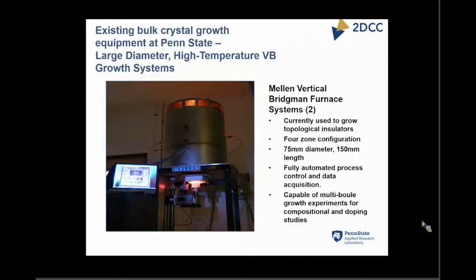And these are the systems that were currently used to start the growth of the topological insulator materials. These are 4-zone configurations. They've got 75 millimeter diameter capability, again, fully automated. And one of the things we've done in these furnaces over the years is use them to grow multi-boule runs. What I mean by that is instead of just growing a single boule, you make an array of boules. And you can do this if there's a fairly narrow temperature range which they solidify over.